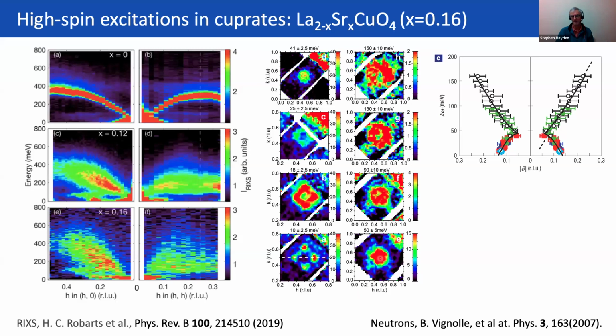where we see this sort of peak at about 50 millivolts, a strong blob at pi, and then below 50 millivolts there's another contribution, which you can see down here, and these four peaks which were observed in the early years after high temperature superconductivity was discovered. Anyway, actually all this data here we took in the superconducting state. So in some sense we've gone back to revisit this and measure at low energies.